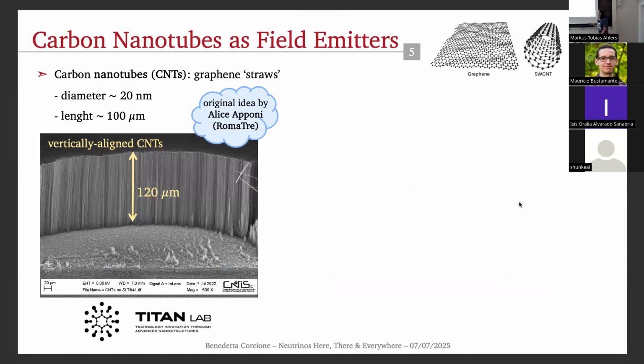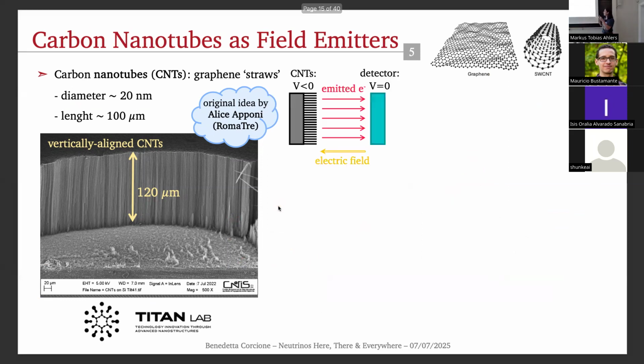So carbon nanotubes are graphene sheets rolled in straws with diameter of 20 nanometers, let's say, and length up to hundreds of microns. We grow them vertically aligned to each other, as you can see here in this picture, in this kind of forests. And we grow them directly in our university in the Titan lab. And the idea is that if we place a sample of nanotubes in front of the detector, we create a kind of parallel plate capacitor geometry. And by applying a voltage to the nanotubes, keeping the detector at ground, we generate an electric field that, once it overcomes a certain threshold, can extract electrons and then accelerate them towards the device.